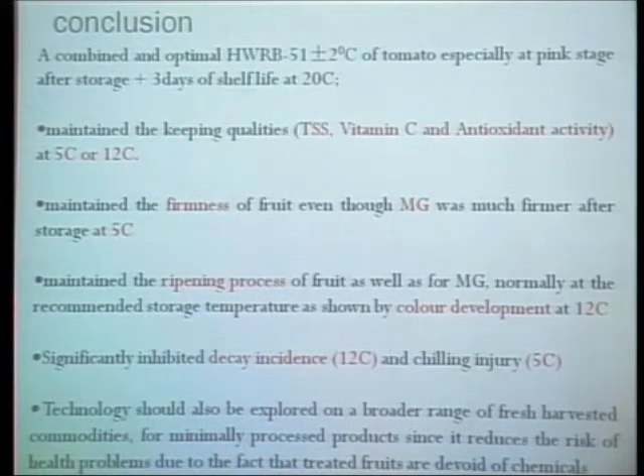We also noticed this heat treatment maintained the firmness of the fruit, even though the matured green was much firmer after storage at this temperature. And this heat treatment also maintained the ripening process of the fruit, as well as for the matured green. And most of the fruit, both the pink and the matured green, ripen normally at this storage temperature, as was shown by the color development in the graphs that I showed. Also, we believe that this heat treatment significantly inhibited decay incidence after storage at 12, and was able to reduce chilling injury.